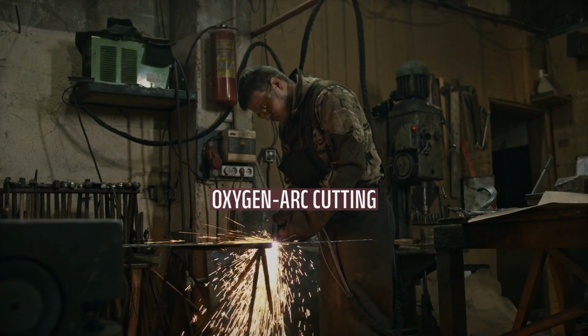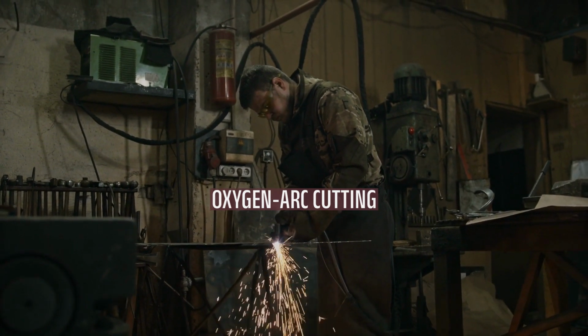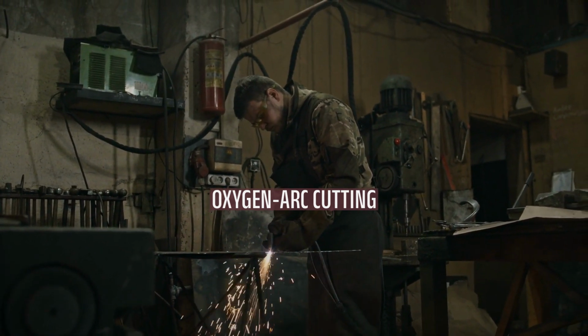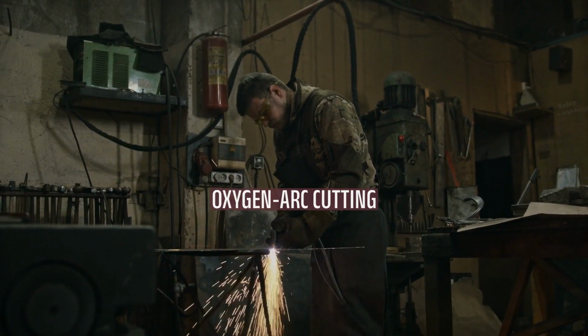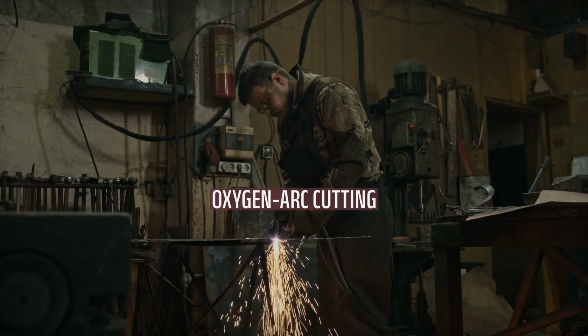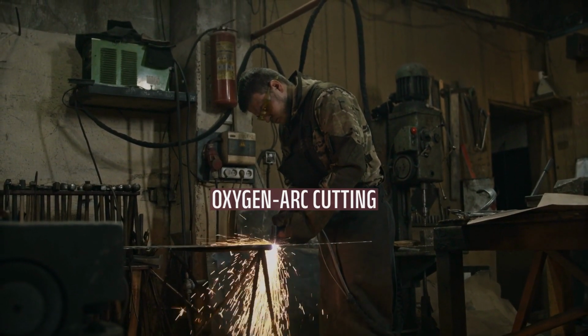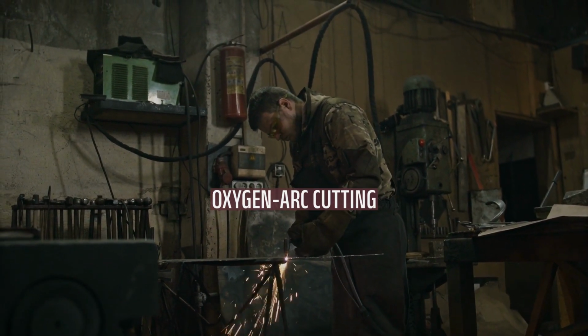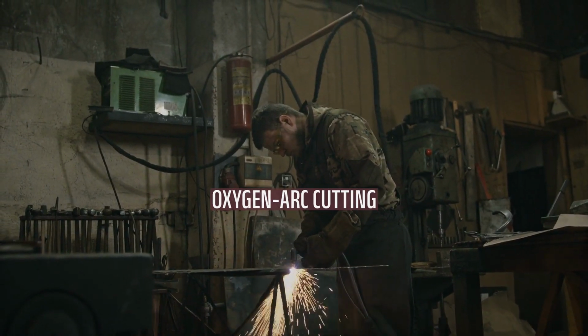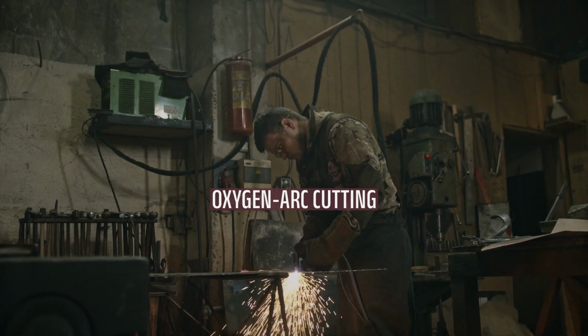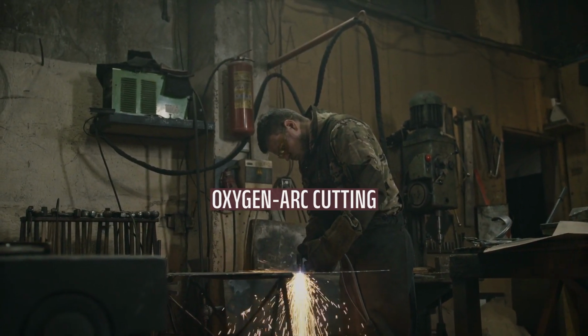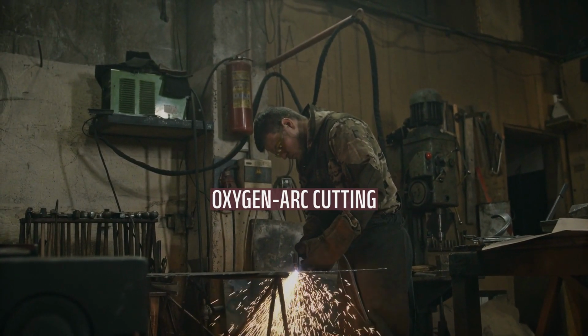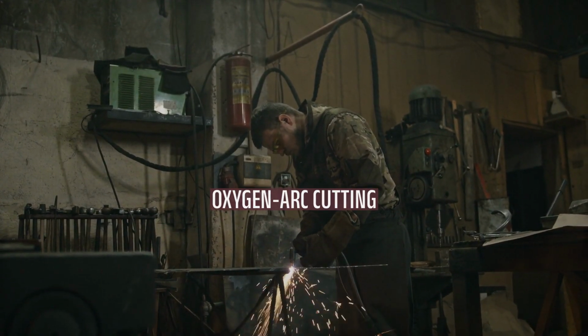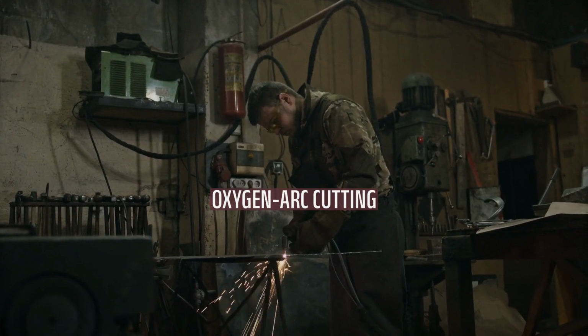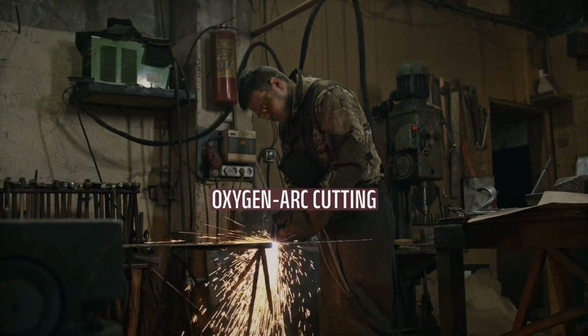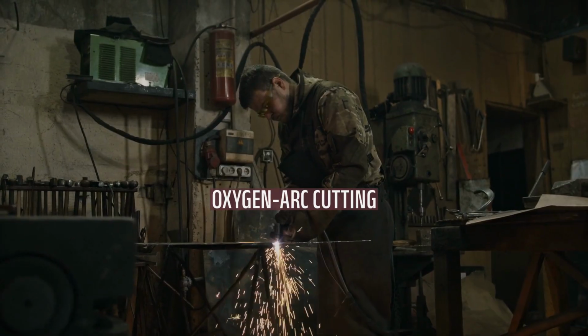The tip of the electrode is consumed and must be replaced frequently as it burns down to a stub. The tubular steel electrode consists of a steel tube with a waterproofed flux coating which is applied during manufacture. A typical electrode is 14 inches long with an inch outer diameter and a bore diameter of slightly less than an inch. The waterproof flux coating is similar to the coating on welding electrodes, and both promotes easy striking and maintenance of the arc, and the gases it produces form a bubble around the arc which keeps the water off for long enough to burn the heated metal under the arc.